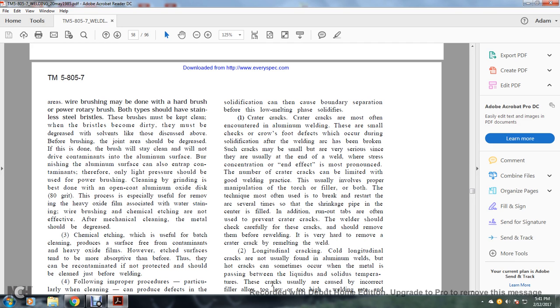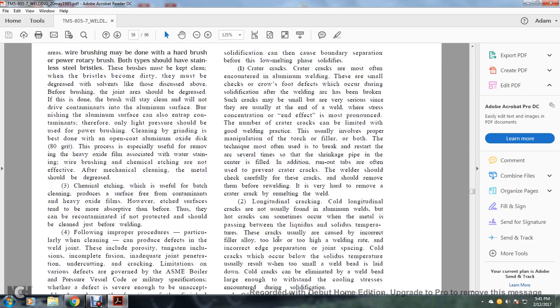They usually occur at the end of the weld and may be serious. Stress concentration and the end effect is most pronounced. The number of crater cracks can be eliminated with good welding practice, which usually involves proper manipulation of the torch and filler. The technique most often used is to break and restart several times so the shrinkage pipe at the center is filled. In addition, run-out tabs are often used to prevent crater cracks. The welder should check carefully for those cracks and remove them before rewelding. It is very hard to remove a crater crack by remelting the weld.